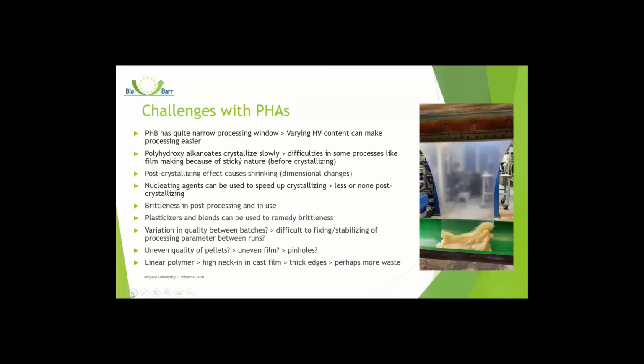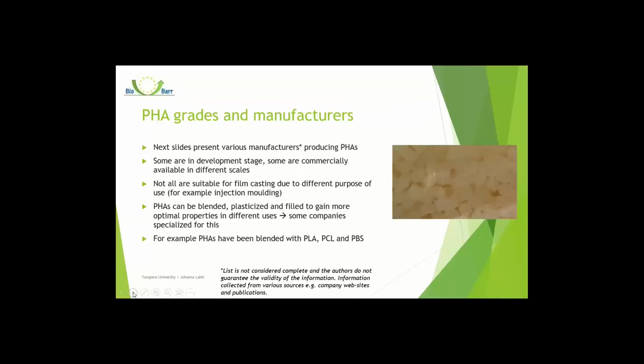Brittleness and the mechanical properties are sometimes challenging in post-processing and also in the end use. Also, there might be some challenges depending on what kind of grade we are using. That is the quality consistency, if there is any variation in the quality of the material, if there is uneven quality in pellets, and so on. These all can affect the processability and can be seen, for example, as defects in the films. And the linear nature of the polymer, of course, may cause some typical features, for example, sometimes this high necking behavior in casting.